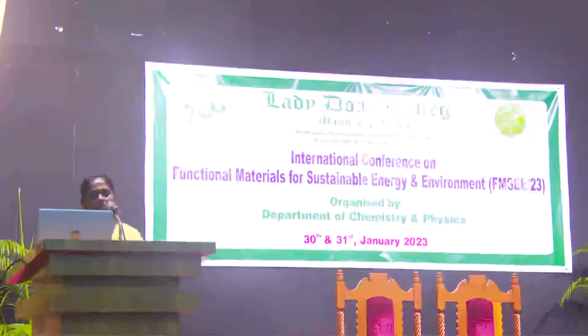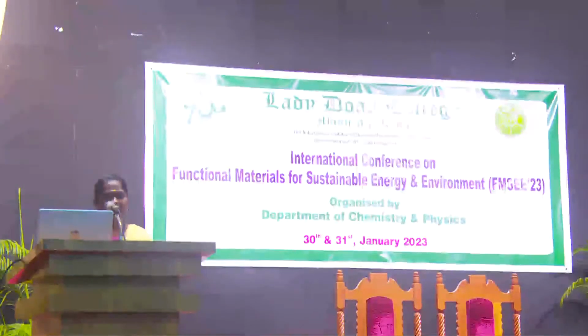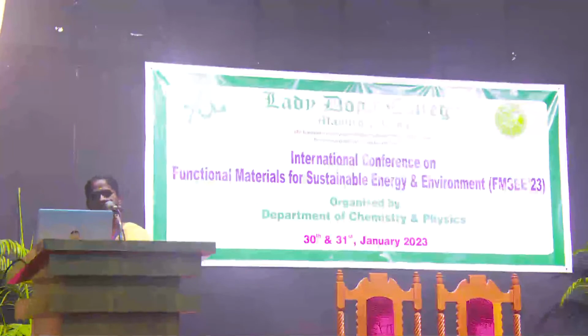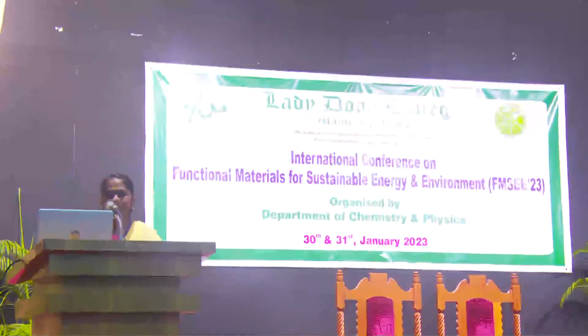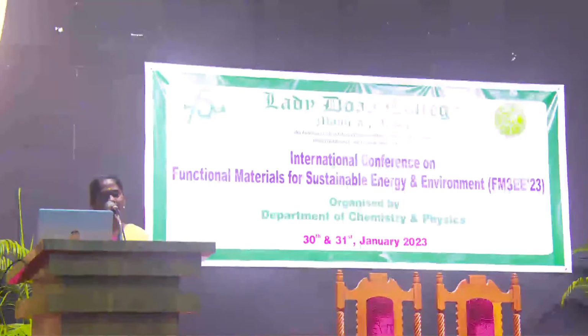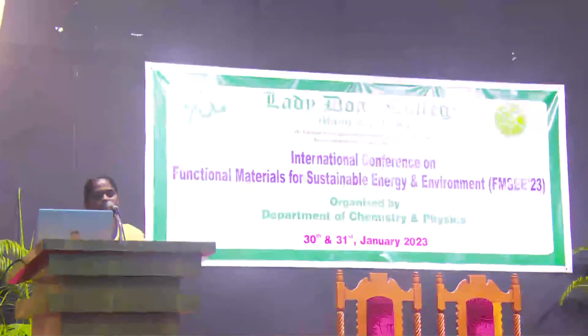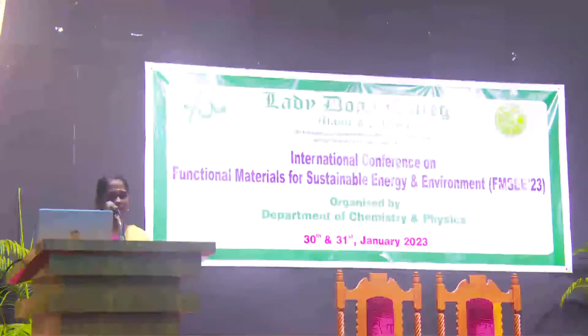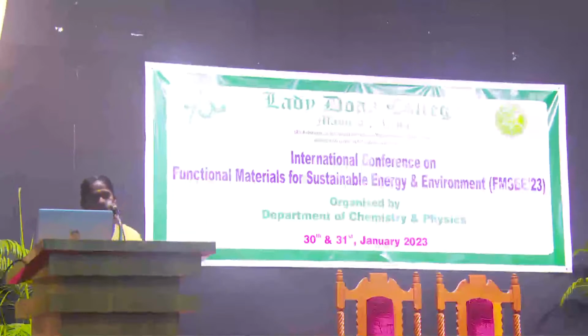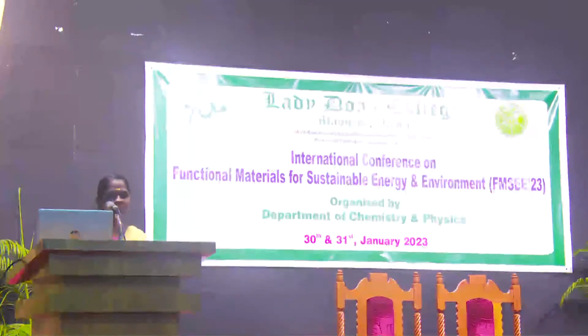This is my XRD pattern and I get some rhombohedral structure. The red color represents with surfactant and black color is without surfactant. And this is my FTIR. In FTIR I get some hydroxyl and carbon dioxide. And my conclusion: the vanadium trioxide particles with and without surfactant were prepared from yellow precipitate, and XRD and FTIR were studied.